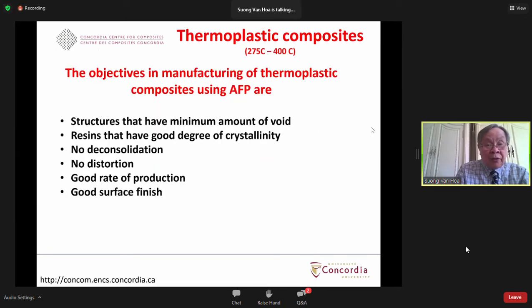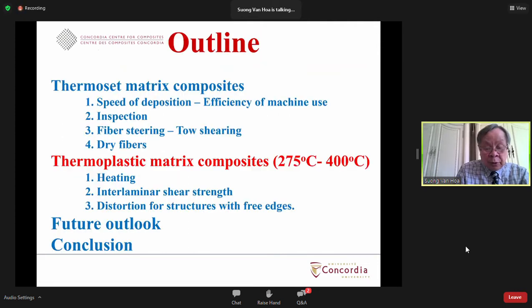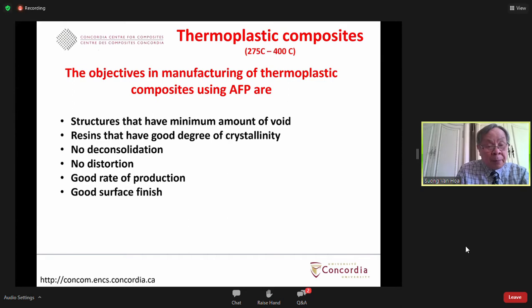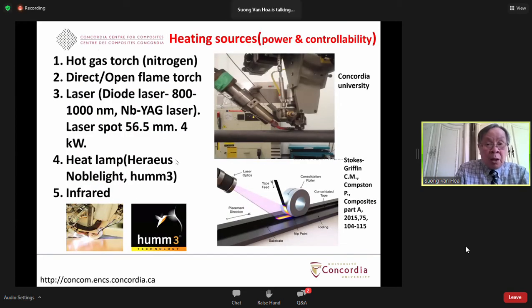Usually the objective in manufacturing of thermoplastic composite using AFP is to have a structure with a minimum amount of void, a good degree of crystallinity for the resin, no deconsolidation, no distortion, good rate of production, and good surface finish. And again, I mentioned there are many issues. The first one here is heating. The heat source for the case of thermoplastic composite has to be stronger than the case of thermoset. That's because you have to melt the resin because of the high viscosity.